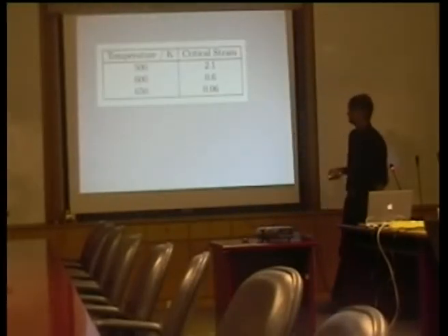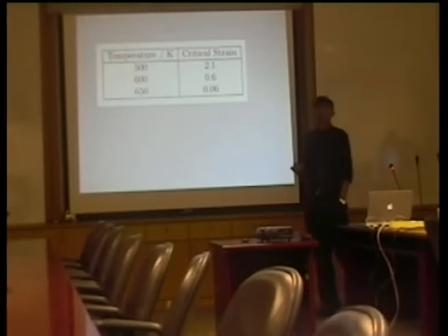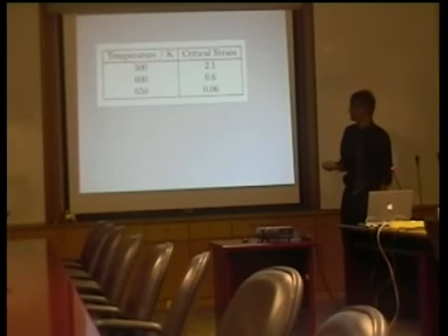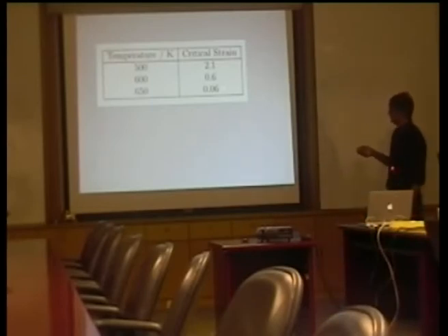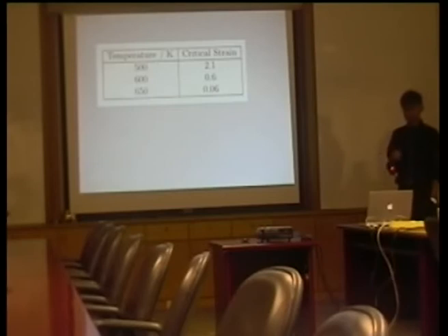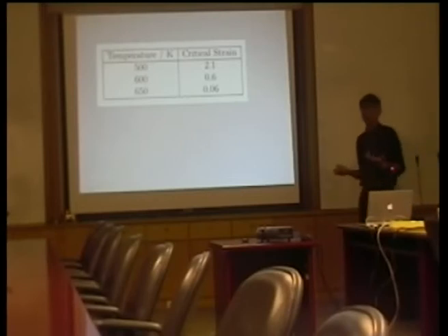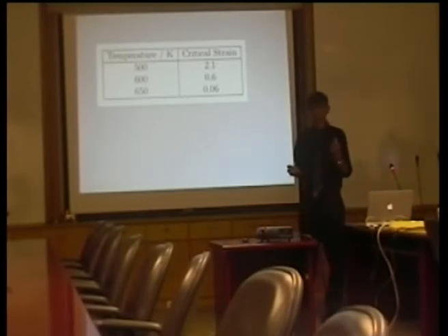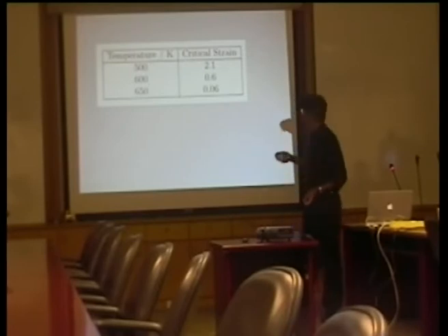And the micrographs I showed you were for transformation at a temperature of around 500 Kelvin. Transformation for a temperature around 650 Kelvin, okay, 377 degrees centigrade. And according to this, the strain at which you should get mechanical stabilization, in other words, the plate should stop growing, is indeed around 0.06. Furthermore, this shows that if I lower the transformation temperature, then the strain would be larger. In other words, the plates would be longer. And that's exactly what we observed.